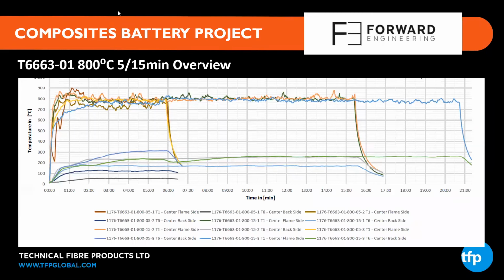So this somewhat complicated graph, I can simplify fairly quickly. This is involving T6663-01, which is a very lightweight intumescent veil. So this is a 70 gram per square meter veil at 0.37 millimeters thickness. On the x-axis, we have time. On the y-axis, we have temperature. And this is one of the 800 degrees centigrade runs of experiments. You can see the top line, the surface of the panel is achieving 800 degrees.